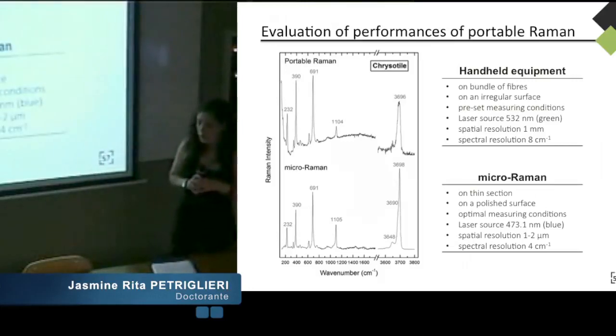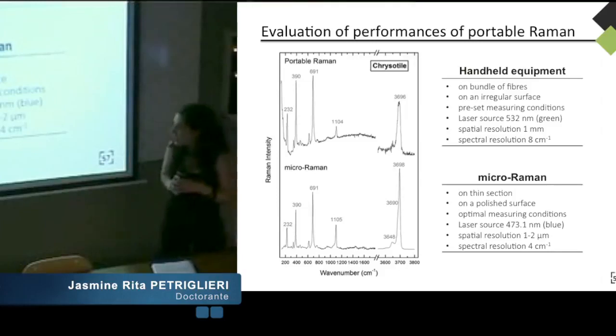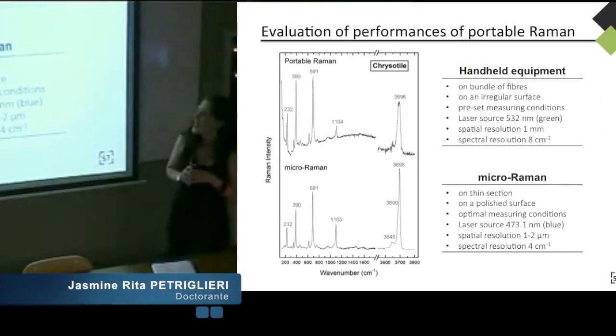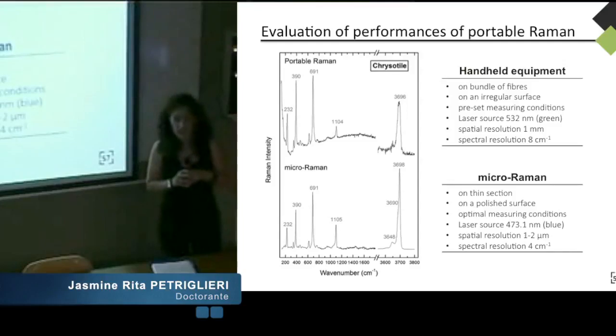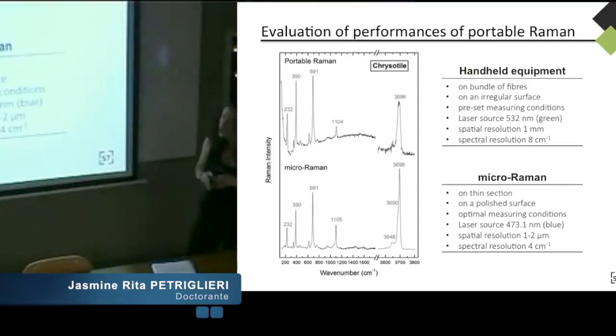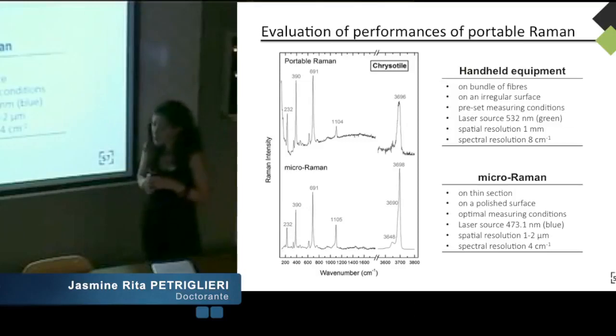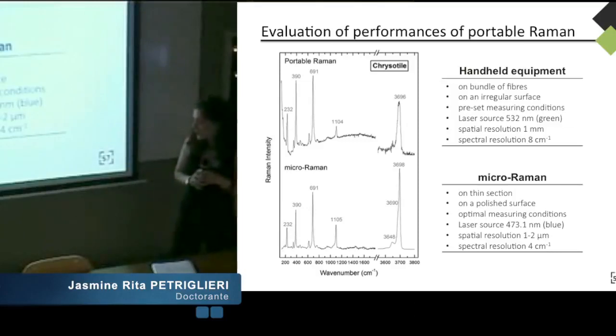A comparison of the performances of the portable Raman to the laboratory device was realized in order to test the efficacy of this technique. And despite several intrinsic limitations related to the compact geometry of the equipment, observing the Raman spectra, we can conclude that the portable equipment allows us to identify all serpentine and amphibole phases.